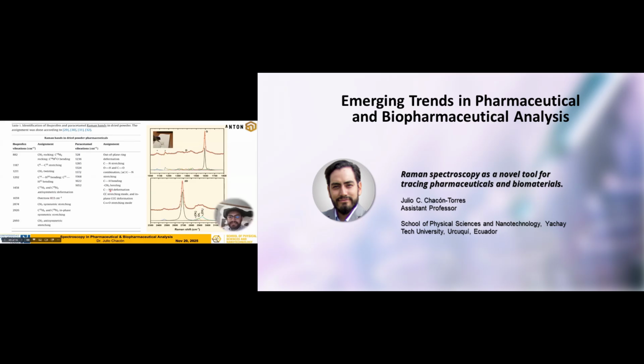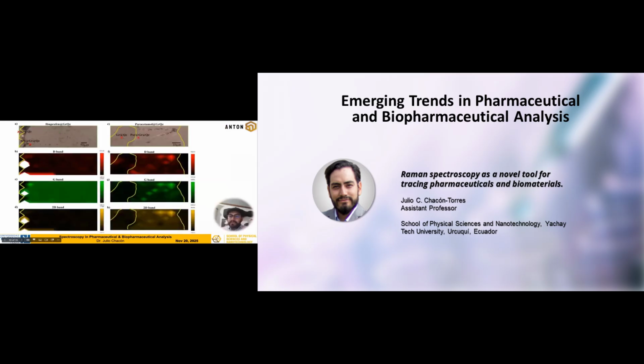And what is more exciting is that for the first time, at least to my knowledge, we have a really well-described fingerprint of paracetamol or ibuprofen, these two pharmaceuticals, in an extremely low concentration. A concentration that cannot be easily detected when you have the whole liquid system, but when you deposit it on graphene, then you look at it and you have the signal appearing there. So we did that system, but we wanted to be sure that the response was really coming from an interaction between the graphene and the molecule of ibuprofen or paracetamol.